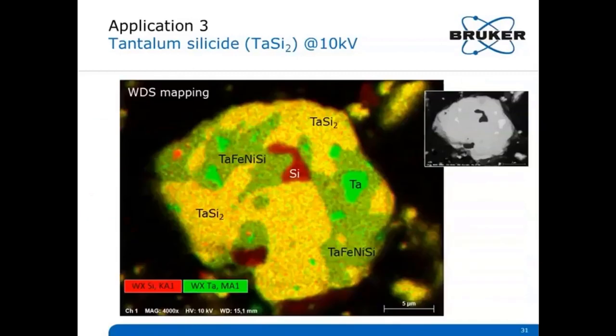Here's a compilation of the result. Here's a WDS map for silicon and tantalum distribution in the sample. Besides tantalum disilicide, marked here with yellow, which is what the sample is characterized as, we also find areas of tantalum silicide which is enriched in other elements such as iron and nickel. These are the olive green areas. And we see furthermore inclusions of pure tantalum, the bright spots here, and inclusions of silicon, the dark red spots here, or red-brown spots.